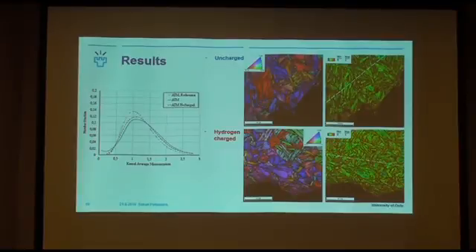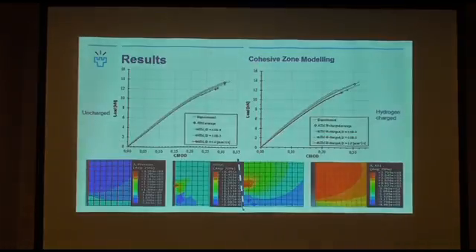Cohesive zone modeling results. The essential thing here in this first case is the distance of this green dot to this gray dot. So due to the successful calibration, we get a very good agreement in the model with our experimental tests.